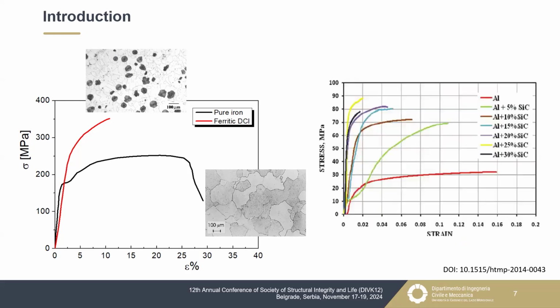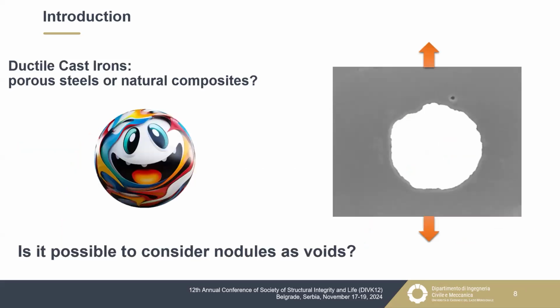Instead, if we compare, for example, the behavior of an aluminum alloy with an increase of the silicon carbide content, we can see an improvement of the stress strain curve. Obviously, other mechanical properties could decrease, so we are simply considering this mechanical property. And at least two different approaches try to investigate the role of these nodules. First of all, the nodules as voids.